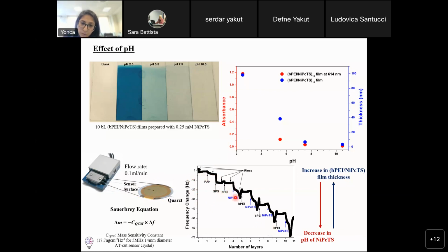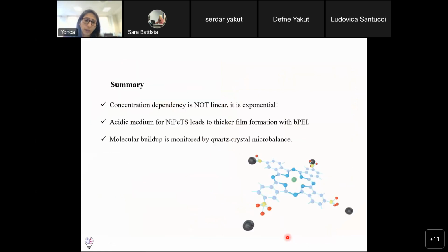And then once I start to introduce the nickel phthalocyanine, you see a sharp decrease in frequency. Here again, once you introduce the branched polyethylenimine, there is a decrease, but it's not so intense. But as soon as you introduce the phthalocyanine, there is a sharp decrease. So actually, this is why we have deposition in a sequential manner due to the addition of nickel phthalocyanine, and it's really nice to see in real time. So in the first part, I can say that the concentration dependency is not linear, but exponential, but it doesn't have to be always the case, because I will show you in the upcoming slides that it's possible to have linear growth as well.